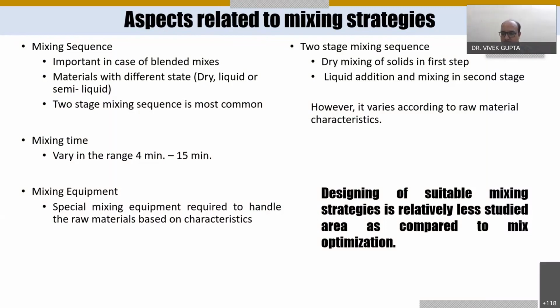If you directly mix the lime and fly ash, it may result in lumps. And if you do not give a proper mixing time, the lumps may go into the bricks and deteriorate the performance of the bricks. So the mixing sequence is a very important aspect, and in the literature, the two-stage mixing sequence is the most common.